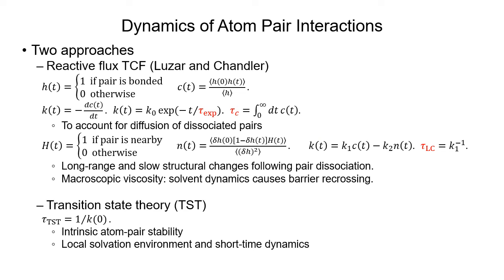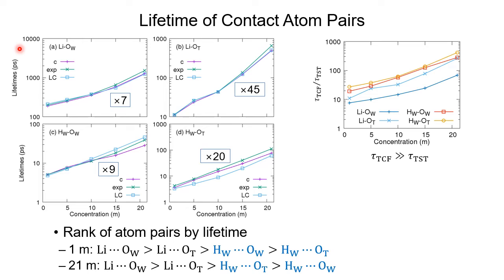We also studied the dynamics of atom pair interactions using the reactive flux time correlation function approach developed by Luzar and Chandler and the transition state theory. These methods reflect different aspects of the molecular interaction and dynamics. Using the reactive flux time correlation function method, we obtained the lifetimes of 4 types of atom pairs, which increase by an order of magnitude from 1 to 21 molal. And the transition state theory lifetime is much shorter by 1 to 2 orders of magnitude, as this plot shows.